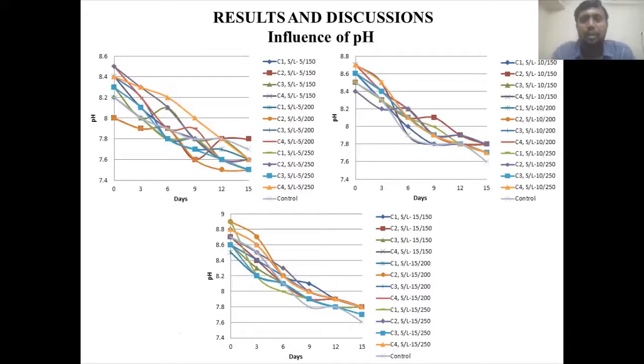Now this is the results and discussion section: the influence of pH. You can see here that from the first day onwards, the pH of the solution is nearly 8 to 8.5. There is a slight increase generally, because the original pH of the culture medium is prevailing at 8 or 8.2. But when you add electronic waste to that, what happens is that the electronic waste is generally alkaline in nature,